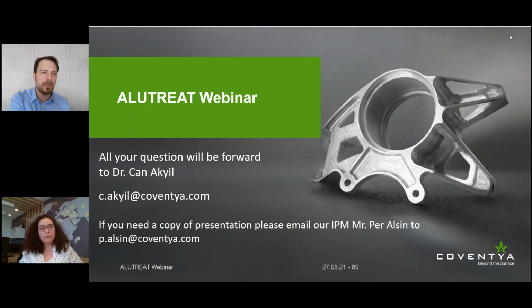The question is, is it possible to match? Well, Pinar, I know that you can do that, but for that, our previous webinar about the pre-treatment is paramount. That means we do not etch the surface just to adjust the surface gloss or the surface roughness. The reason why we're using an acidic base and an alkaline base is, quite frankly, to remove some of the intermetallics, and create a zone which is richer in aluminum, so that you can grow a better anodic oxide. So is it possible to match? Yes, but you need to use the process in its full extent, which means including the pre-treatment, not just for cosmetic etching, but for, as we say in plating, conditioning the substrate.